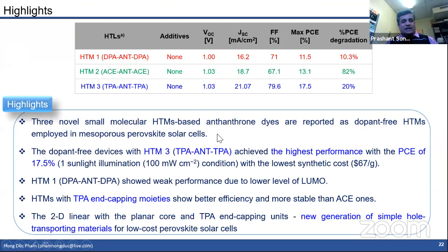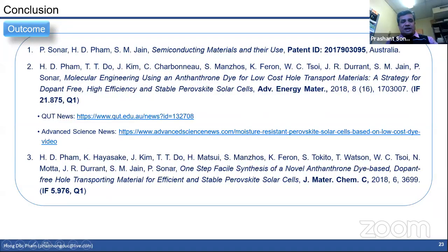And that yielded the conclusion of those 3 HTMs. We could achieve a really high efficiency of 17.5% among these 3, and the PCE degradation is only 20% in case of HTM3, whereas it is 10.3 for HTM1. And we got a couple of papers on that, one in Advanced Energy Materials and another in the Journal of Materials Chemistry, and there's also a filed patent.